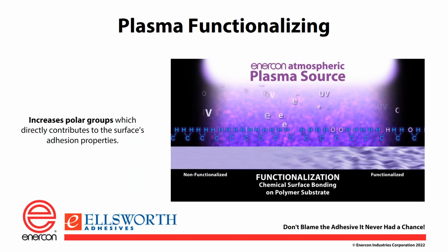Lastly, on the next slide, we're going to talk about functionalization. And this is increasing the polar groups on the surface. Now this is a little bit more complicated. We're actually changing the outermost molecular layers and adding polar functional groups like O2 groups, OH groups. And what that does is increases the surface energy. I mentioned before that if you Rain-X your windshield or you wax your car, what you're really doing is decreasing the surface energy, so that the water in that case will just roll off and it'll be easier to see, or your car will stay clean. What we're doing when trying to bond is increase that surface energy.